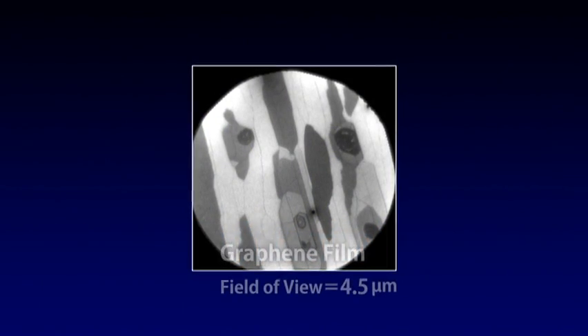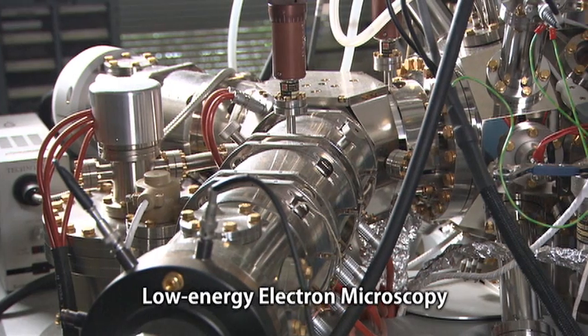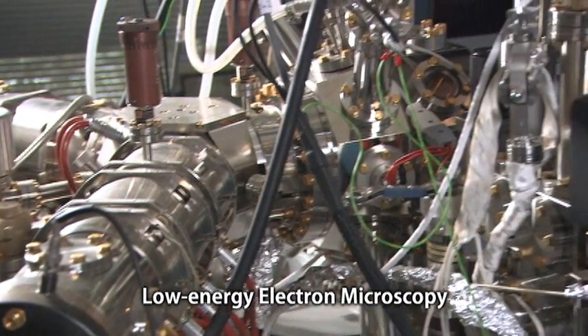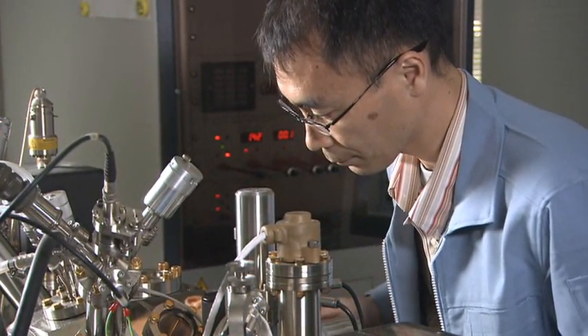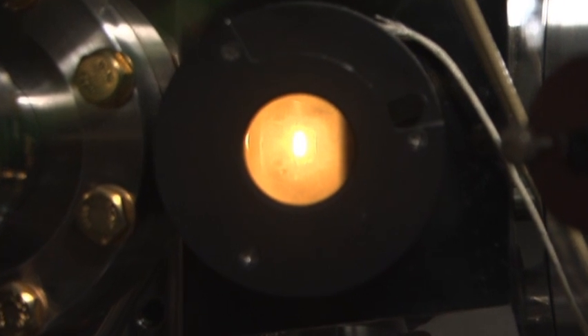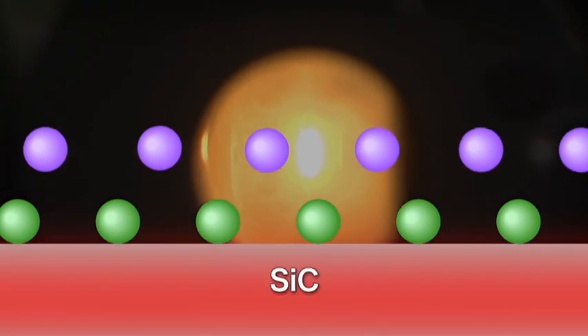However, it will not be possible to develop a manufacturing method without a better understanding of its structure and properties. One promising method for manufacturing graphene substrates is to decompose silicon carbide thermally and remove silicon atoms.